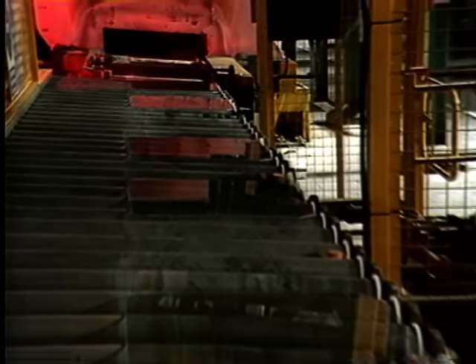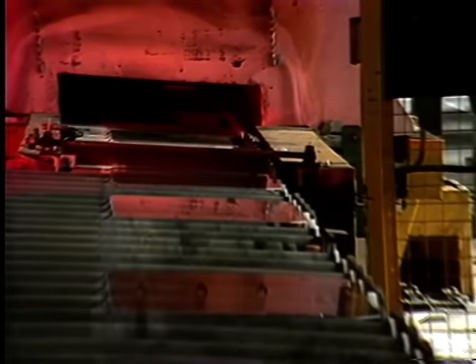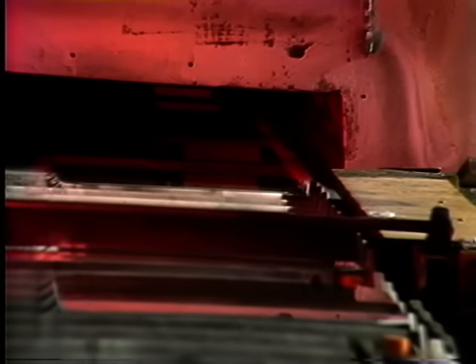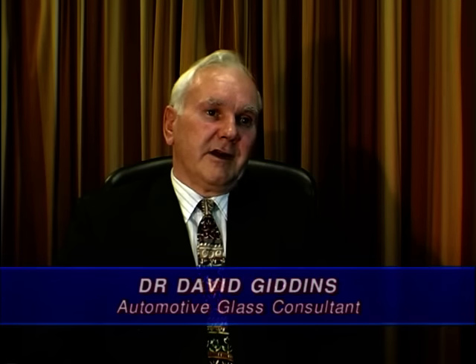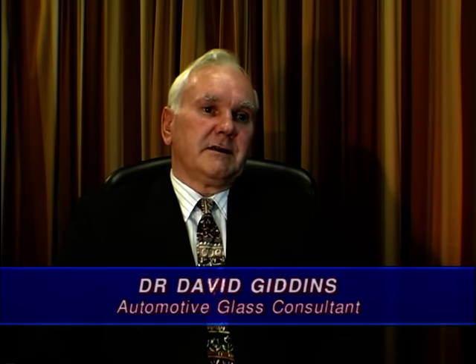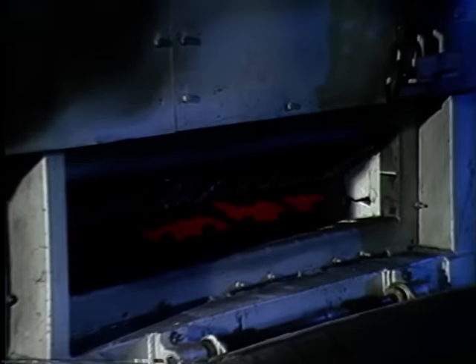It's toughened by heating ordinary window glass to around 630 degrees centigrade and chilling very rapidly, which puts a surface compressive stress into the glass, making it very strong to massive impact. That's obviously a benefit. The stress is built into the glass by that process. If it is released by the layer being penetrated by a sharp object, it causes the glass to shatter into tiny fragments,